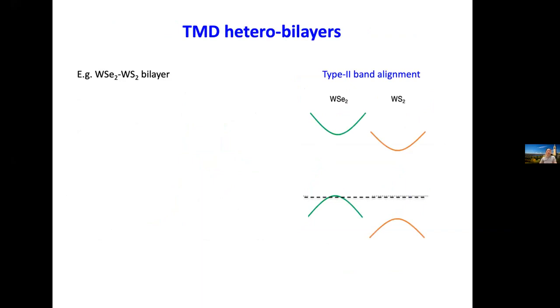So when two monolayers, in this case tungsten selenide and tungsten sulfide, are overlaid, they form a type 2 heterostructure. When we sweep a Fermi level, holes first dope into WSe2 and electrons first dope into WS2 layer.